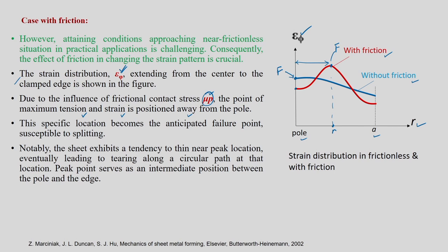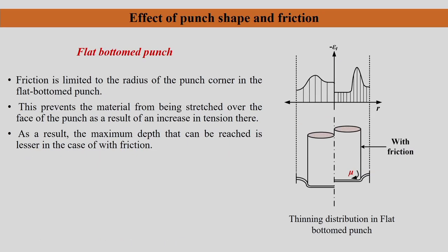So, you can also see that this fracture, this failure location could be circular in nature. From the top view, you can see that this R location is going to be there at any radius in the circular diaphragm, is it not? So, it may split, depending on how instability develops, in the entire ring of the circular path, between the peak and the gripping region, somewhere at a distance of R it will fail. This is the main difference between the with friction and without friction case.